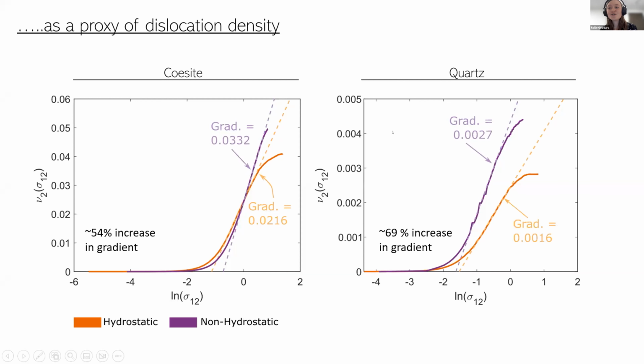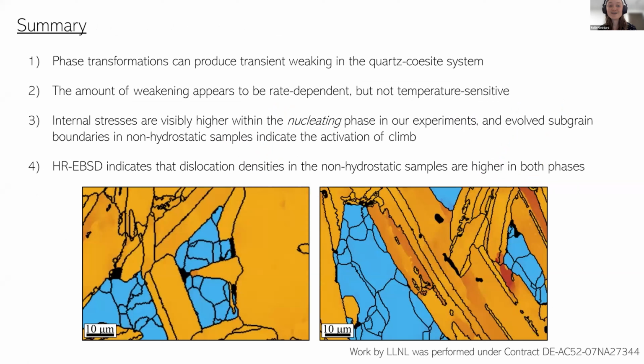example. Also, because we're doing it for quartz, we can see that despite it looking like there is no deformation occurring in the quartz visually, there is a higher gradient for the one that is non-hydrostatic comparative to the hydrostatic one. So when you're going through this transient weakening, we are deforming both the quartz and the coesite, but we're deforming the coesite more. Sadly, I don't yet have any conclusions why we're deforming the stronger sample rather than the weaker sample when we go through this. But what we found is that we've shown that we do get this transformation induced weakening of the quartz, or when you go through the quartz coesite system.